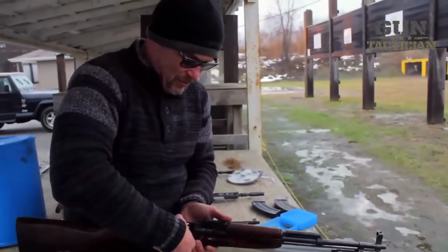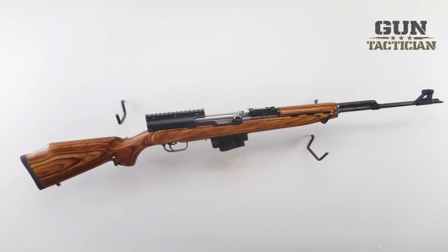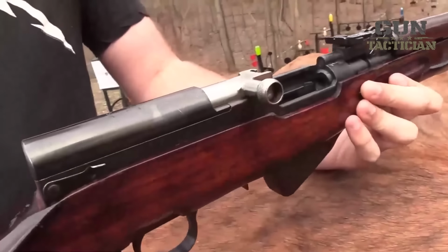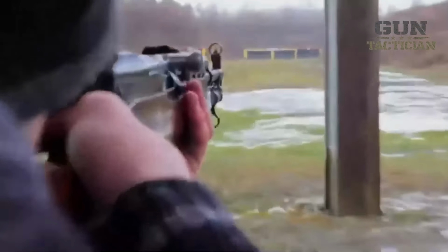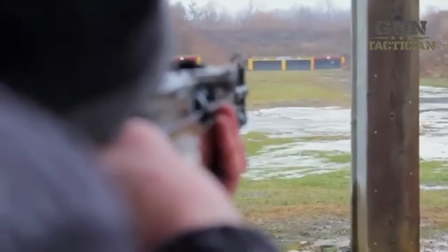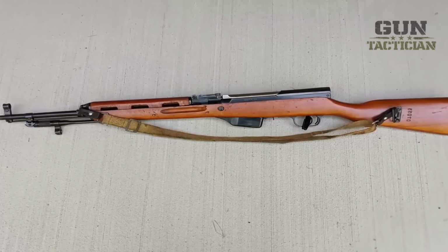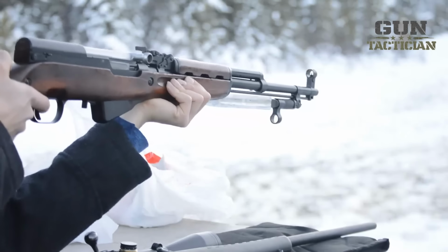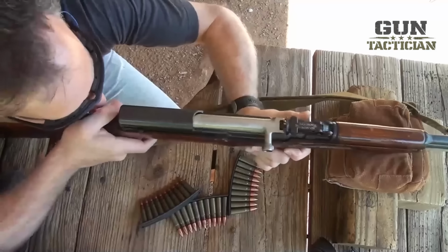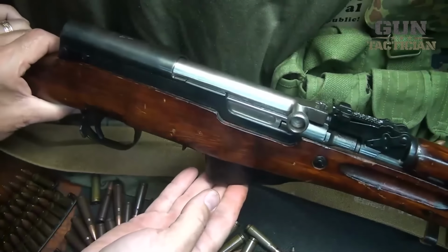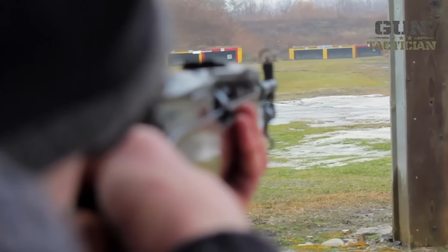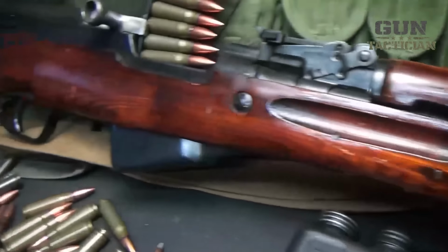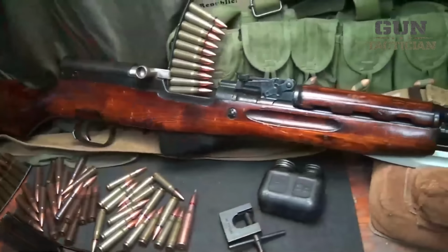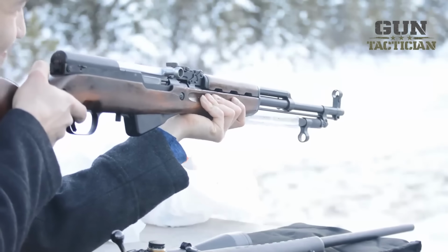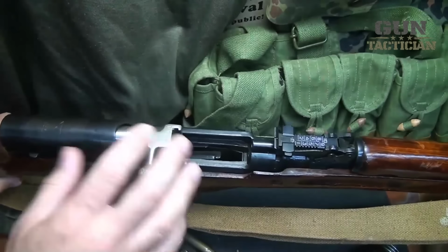Here is the metallurgy. A chrome-lined barrel has a layer of electrodeposited chromium applied to the bore and chamber. Chromium has a Vickers hardness rating of around 1000 HV compared to roughly 200 HV for the carbon steel underneath it. That means the surface your bullet contacts and your gases erode is approximately 5 times harder than the steel it is protecting. The result is dramatically reduced throat erosion, the area just ahead of the chamber where heat and pressure are most intense. On a non-chrome-lined barrel, in hard use, throat erosion is the primary mechanism of accuracy degradation. On a chrome-lined barrel, that process slows down so significantly that military chrome-lined barrels routinely last 20,000 rounds before accuracy begins to suffer.